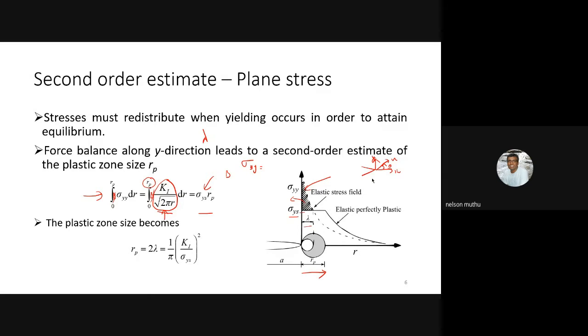So in this case, along theta equal to 0 degrees, this direction, if you see this carefully, along this strip, along this ligament, let me use this word ligament, we want to see how much is the length of the plastic zone. So if you do this force balance due to elastic field and elastic perfectly plastic field from the span 0 to RP, you are going to get the value of RP as 2 lambda. That means your length of the plastic zone using the second order estimate is twice the length of the plastic zone using the first order estimate. So that becomes very convenient.